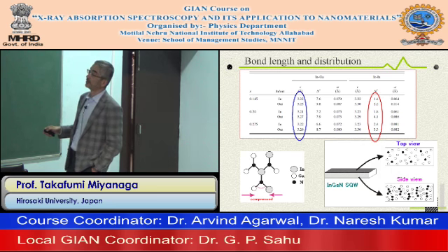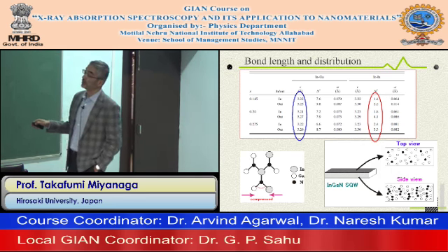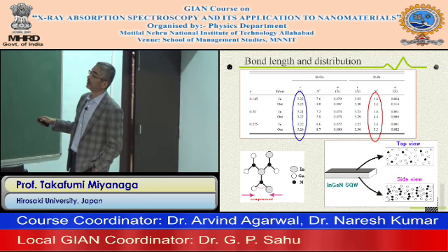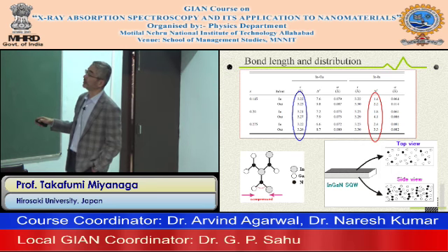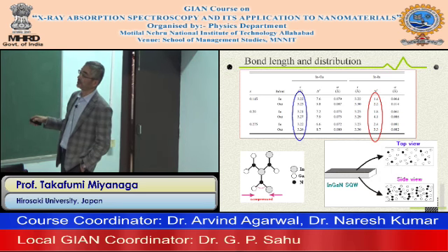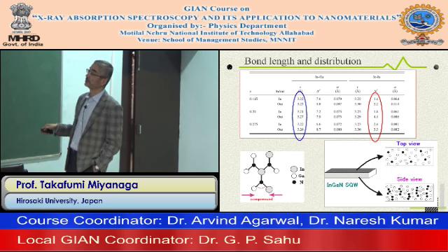And secondly, we checked the effective coordination number of indium-indium. For all three samples, the indium concentration is larger out of plane, the vertical direction, than in plane, in the AB planes.